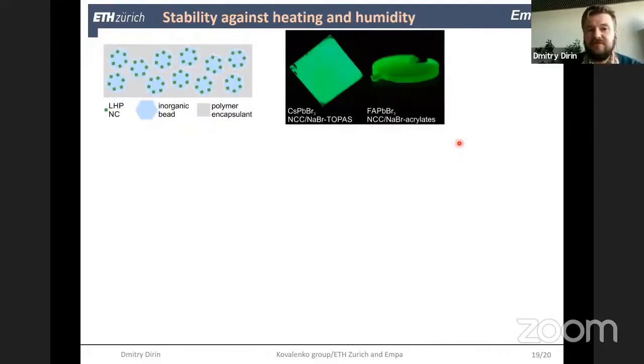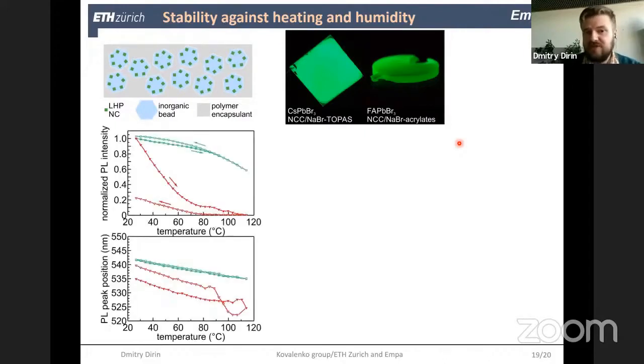In real life, we also need good stability against water. And obviously, sodium bromide is not the ideal shell if we want to stabilize this material against water. But since we now have better stability against other polar species, we can encapsulate this material in polymers, and we can also do in situ polymerization. So we disperse this material in, for example, acrylates and then polymerize. Colloidal particles in this case cannot be used.